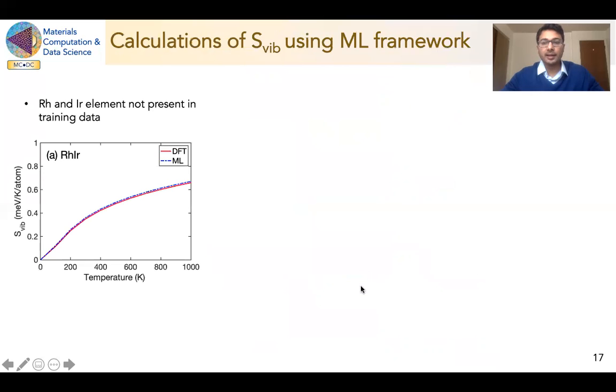So here in this slide, I'm showing the calculations of vibration entropy using machine learning framework. The first example is for rhodium iridium alloy. Vertical axis is the vibration entropy and the horizontal axis is the temperature. And you can see that the framework gives vibration entropy very good across the temperature. The important point to note here is rhodium and iridium element is not present in the training data.